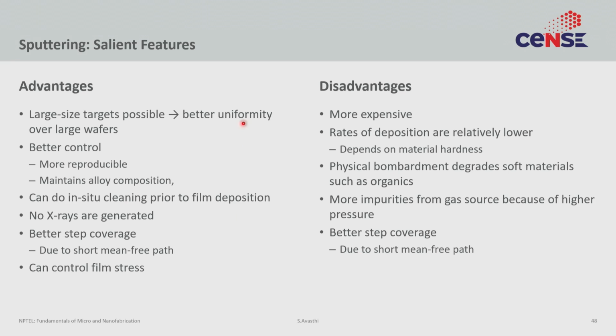When you do this, you still have to be careful that in order to make sure that most of the voltage drop happens near the target, the chuck or the substrate size must also increase, but that is often easily done. Another advantage is better control, more reproducible films, and especially more reproducible alloy deposition. Evaporation does not allow you to do alloys, sputtering does. You can do in situ cleaning because you have a plasma, and you remember the lecture on dry cleaning where we were using plasma to clean the substrates. Well, here we have plasma in situ, so you can just change some parameters, change the direction of the electric field, and thereby clean your substrate before you start the deposition.